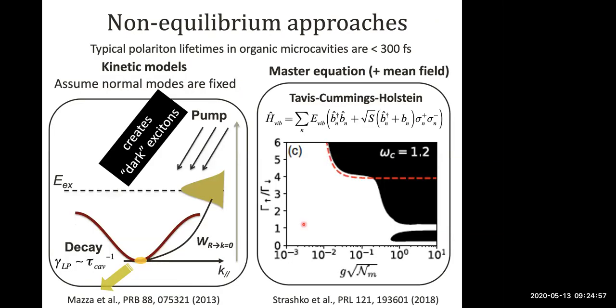In the context of organics, one of the most interesting prospects for Polaritons is, of course, to simply realize very low threshold sources of coherent light. Electrically pumped organic lasers continue to be an outstanding challenge in the field. And if Polariton lasers can have a threshold which is several times lower than a comparable organic laser, then this would allow for electrical injection potentially.